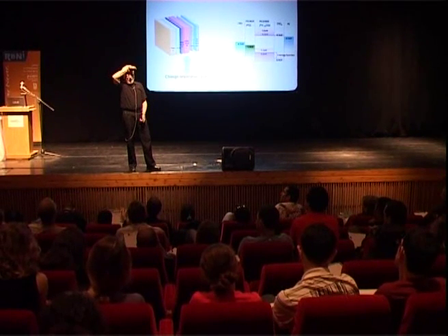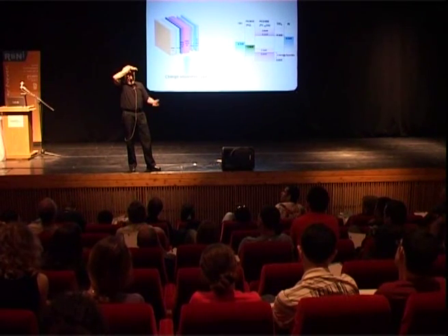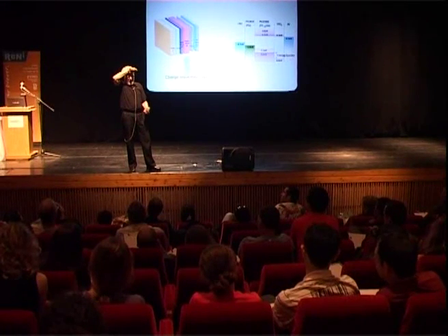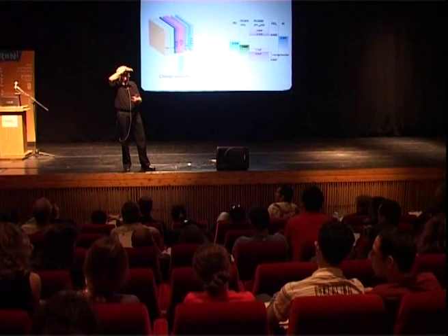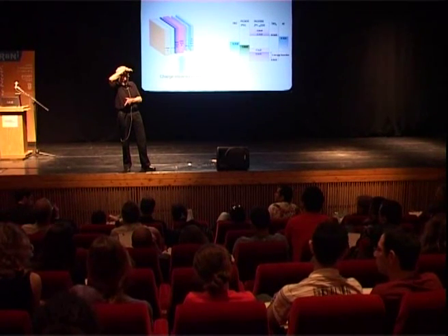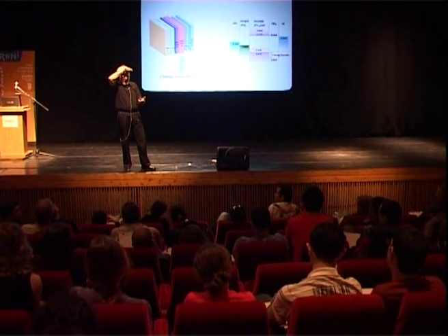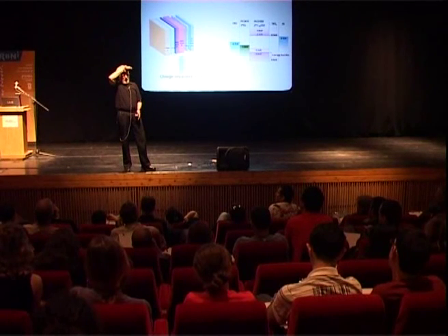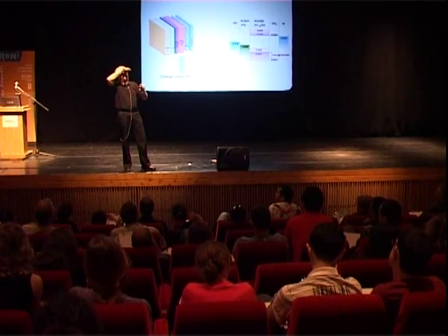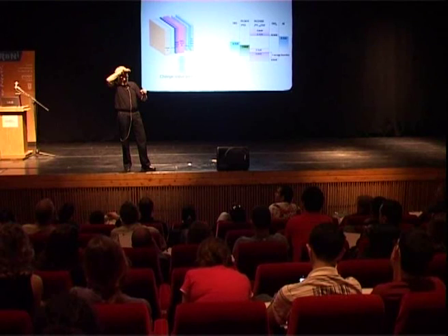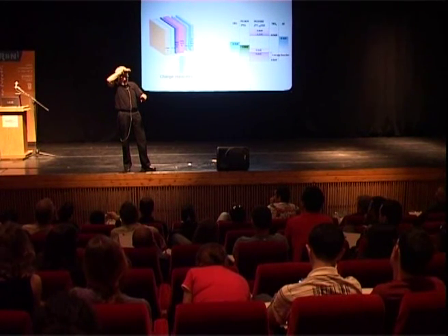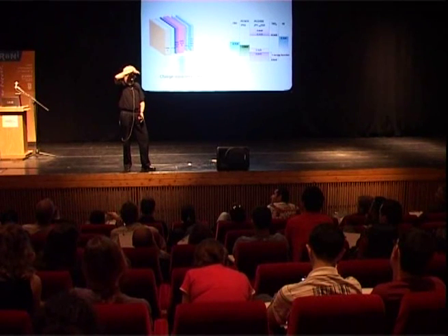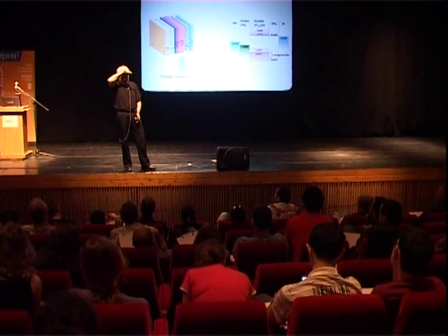One of which is that half of them are metallic, and metallic would be shorts. So first of all, you have to separate out the semiconductor from the metal. That's being done; people are learning how to do that. The other problem is that the semiconducting nanotubes have quite a small gap, so you're going to lose all that energy in the charge. People have tried this. It doesn't seem to be the right way to go.